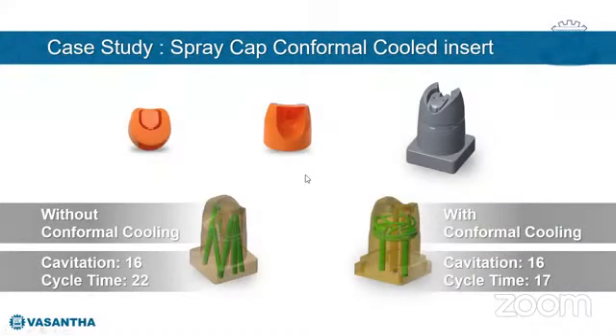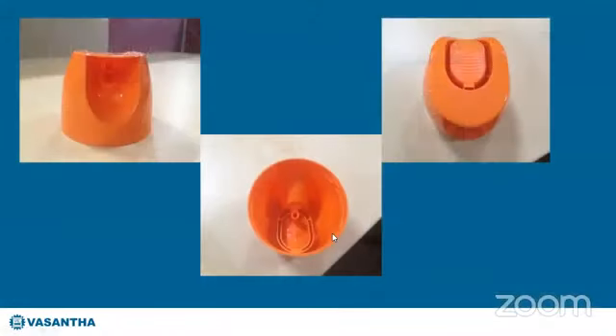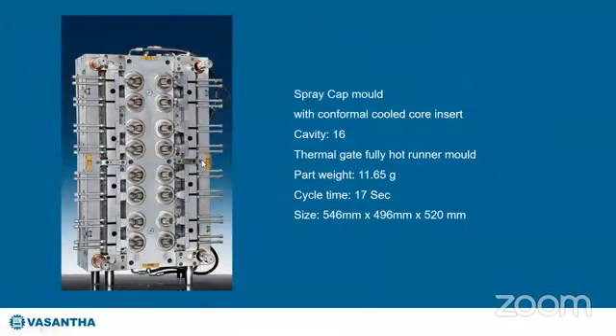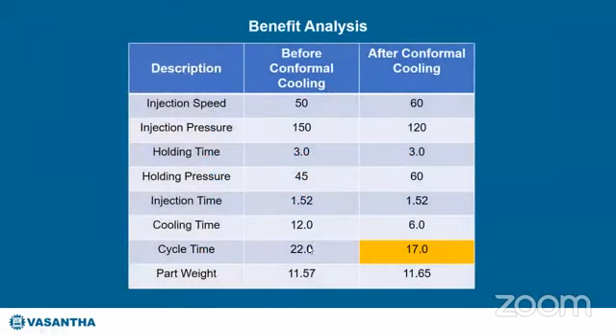This we have seen already in the design, wherein we had a 22-second cycle time using conventional cooling, and then we could reduce it to 17 seconds. This was the part produced. That was a 16 cavity mold, 2x8 layout, which we can see on the left side of the screen. We can see the cooling time from 12 seconds, we were able to reduce to 6 seconds.